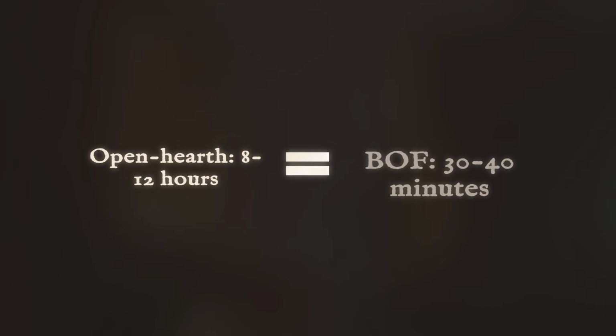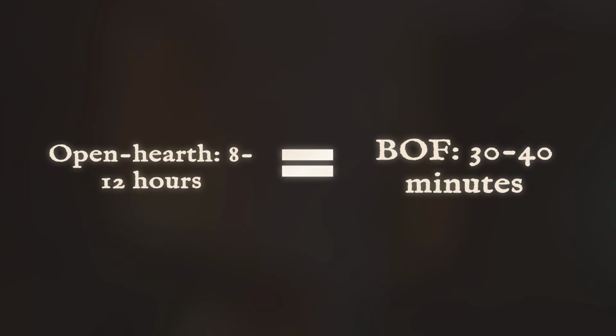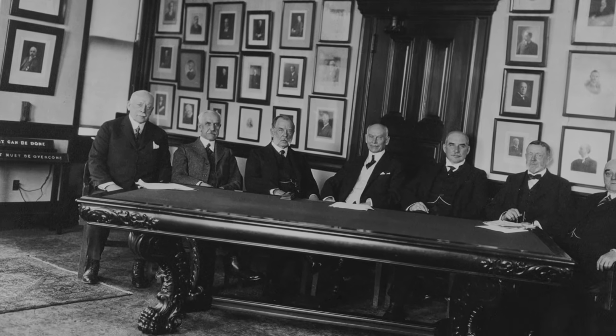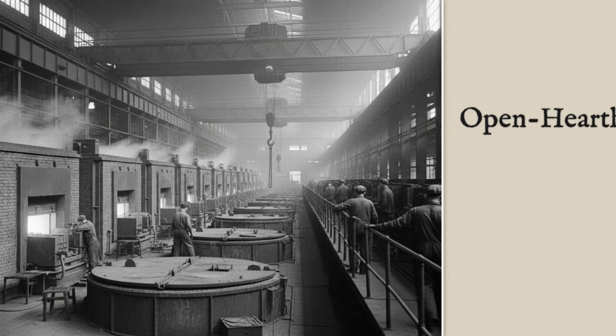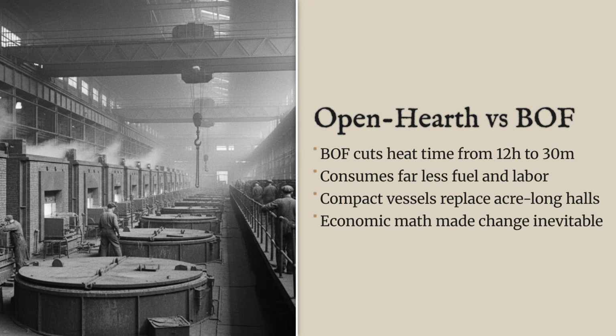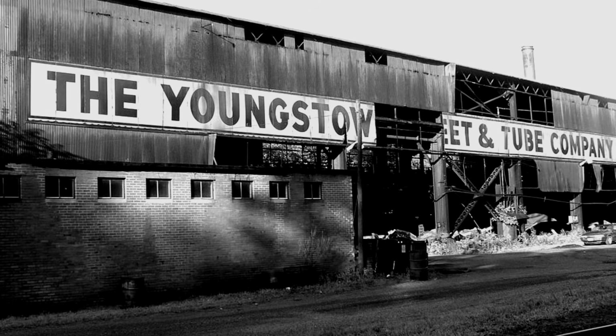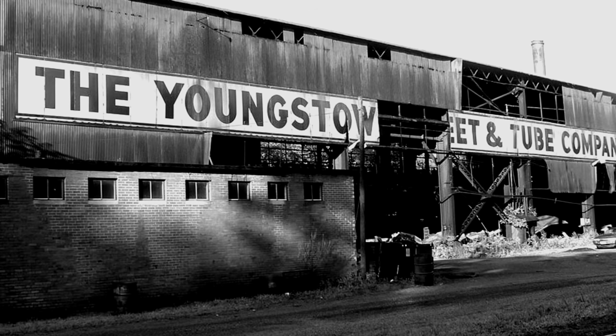A basic oxygen heat took 30 to 40 minutes instead of 8 to 12 hours. For steel companies calculating the economics of a post-war expansion, the math was straightforward. The Open-Hearth furnace, with its 12-hour heat cycle and its enormous fuel consumption and its building-length infrastructure requirements, was becoming an expensive way to do something that could be done faster.